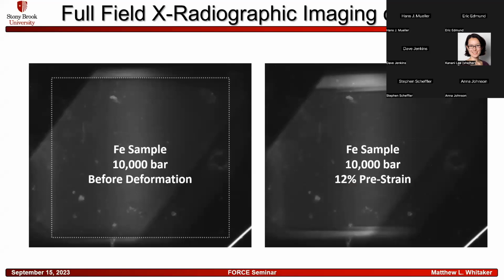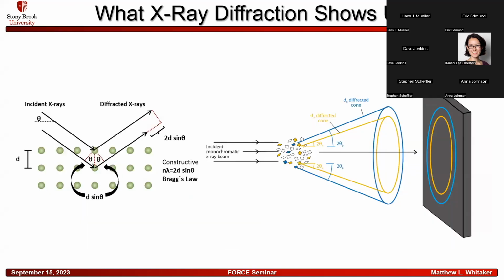And after we did the addition of the pre-strain, you can see that the sample has significantly changed its dimensions, and it's become 12% shorter in the process. And that's exactly what we were looking for in the experiment. So now, what does X-ray diffraction show us?